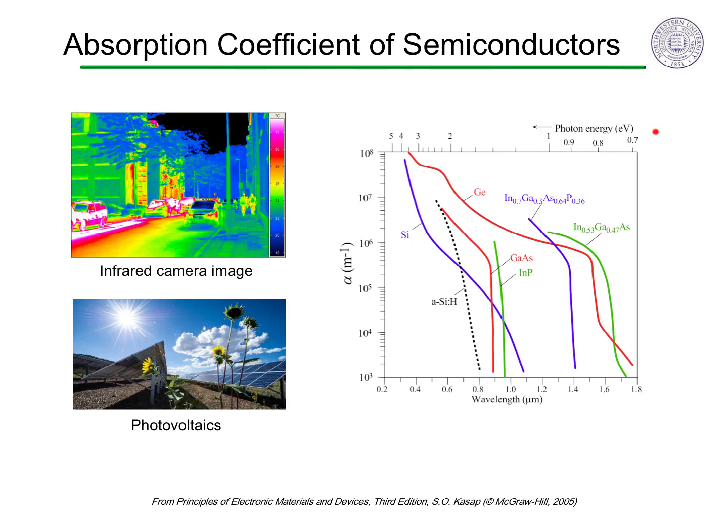The absorption coefficient of various semiconductors are compared here as a function of wavelength. You can spot semiconductors with direct band gaps as they have much sharper absorption. Silicon makes a good window for infrared cameras as they absorb visible light but let infrared light transmit to the detector. The indirect band gap makes silicon less absorbing to visible light than gallium arsenide, so thicker silicon wafers are needed than gallium arsenide for photovoltaics.